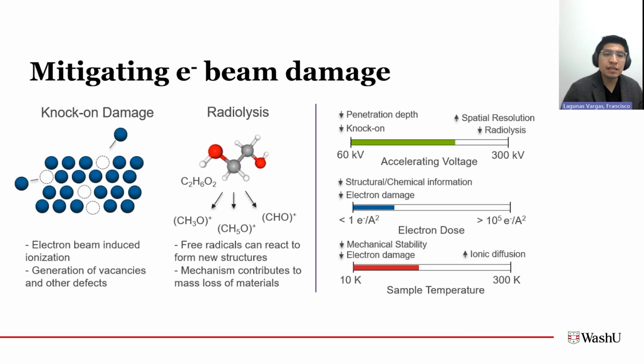Because typically, if you want to avoid knock-on damage, you go to very small accelerating voltages. However, at lower accelerating voltages, you see an increased effective radiolysis. So you would typically go to very high voltages to avoid radiolysis, but then you're going to be worried about knock-on damage. The other thing that we can work on, or that is a careful consideration, is the amount of electrons that we put into our sample.